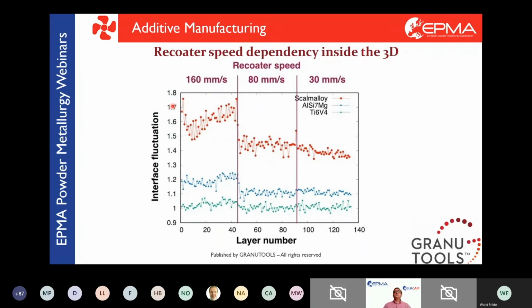So from that experiment, I can tell you that the titanium powder is the best one, followed by the aluminum alloy, followed by the scalmalloy. I can sort those powders and discard the powder very easily. So this was the goal.